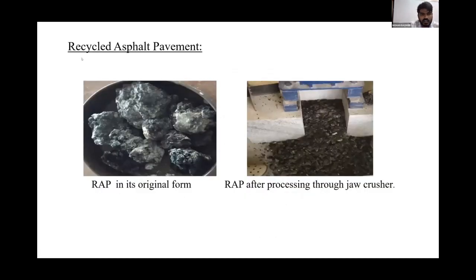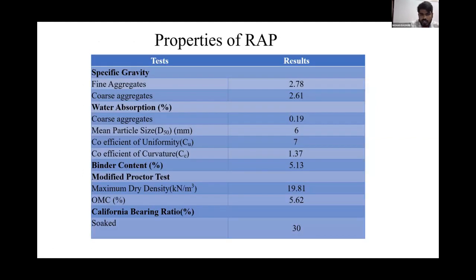Another material used in the study is recycled asphalt pavement, which is construction and demolition waste, dumped as waste on either side of the roads. We use that material in our base mix in the present study. The first figure shows the RAP in its original form, and the second one is the processed RAP, which is processed using a jaw crusher. Here we have got the 20 mm down size RAP fraction by using the jaw crusher, and the rest of the coarser sizes like 40 mm were prepared manually, and that mix was used for the base mix.